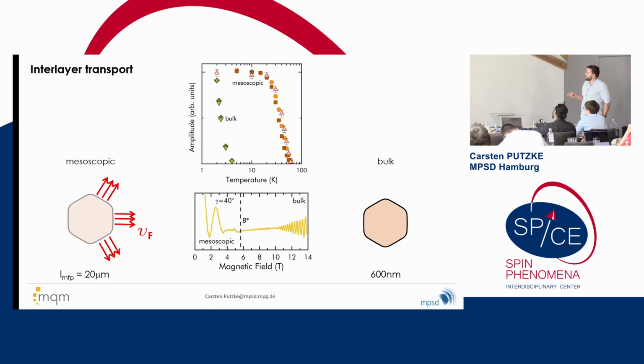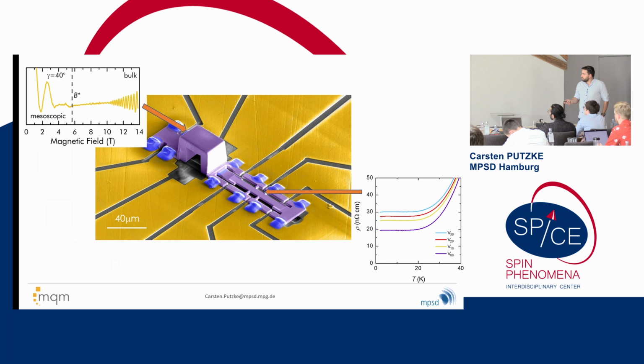You can see those up to about 60 Kelvin, and that comes from the fact that the temperature dependence of this mean free path is pretty flat, and you see those all the way up to the point where your energy scale becomes on the order of your Fermi surface warping, so you can't distinguish which part of the Fermi surface these come from anymore. Then you start to lose those once you have enough temperature smearing to really refine your Fermi surface. So there you can already see that you really have two very different effects. And again, the reason why we can observe that is because we have this property to look at in-plane confinement versus z-axis confinement of these materials. Okay?